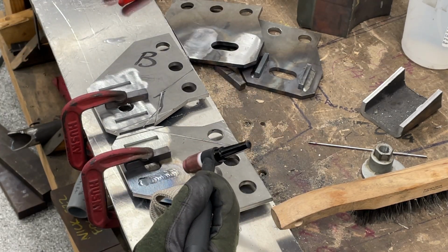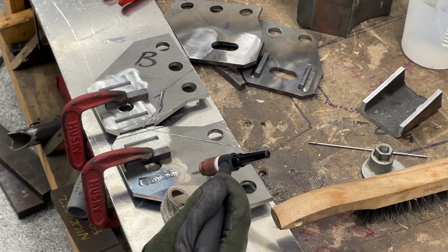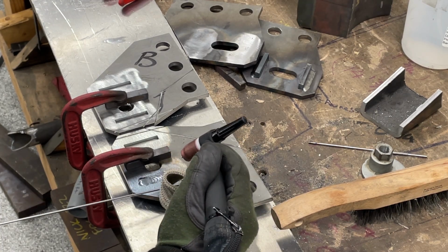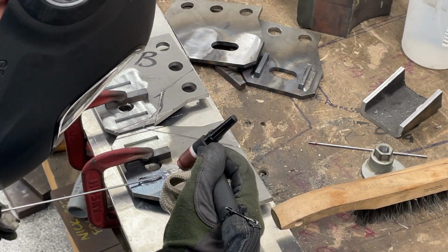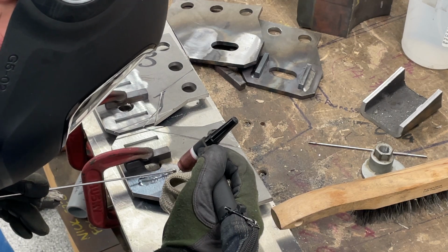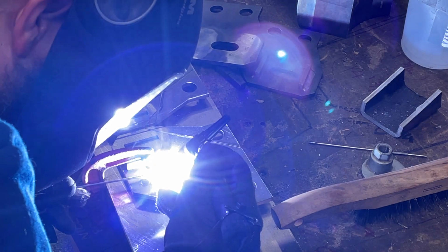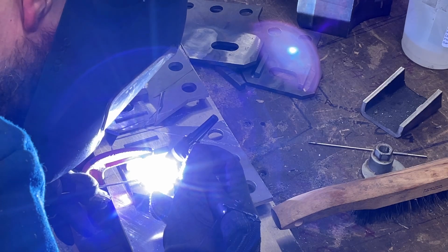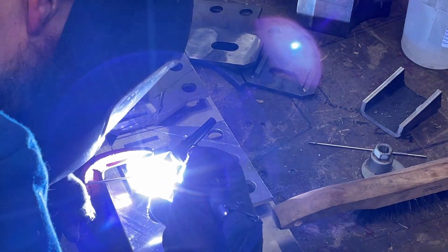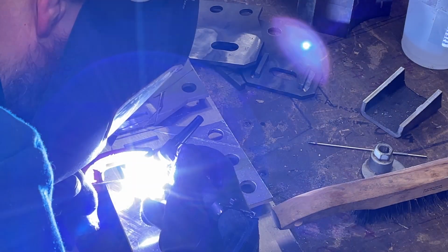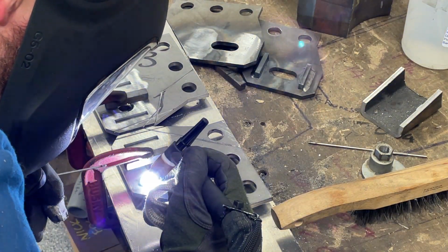So in industry, when we wonder about the temperature or how hot the part is during our welding, we call that interpass temperature. Preheat is the heat before you weld. Interpass is the temperature while you are welding. Fill and chill, make sure you get that puddle started. And now we're going to weave back and forth, making sure we cover all of our previous weld beads. Making sure we don't leave any grooves or valleys, stuff that we don't have to fill up later. Make sure you don't burn your fingers. You could really do that here. As soon as I've filled it up, let's taper it off. Slowly turn off that arc.